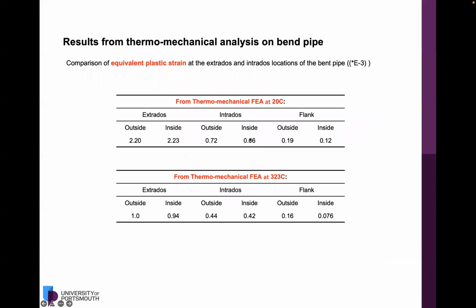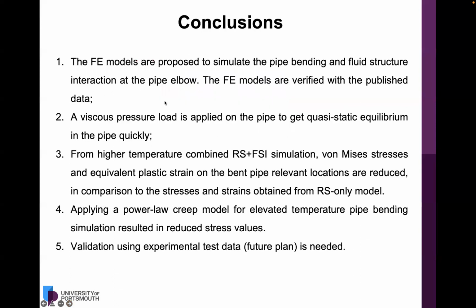We can also obtain the equivalent plastic strains, which is very useful for either fatigue or creep life assessment. So in conclusion, the finite element models that we are proposing can simulate the pipe bending and fluid structure interaction at the pipe elbow. And we can, at the moment, verify these models with the published data. Of course, we are planning to validate our models with experimental test data, our own experimental test data, in the near future.